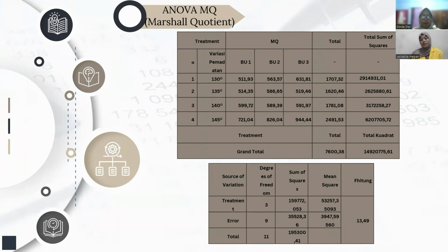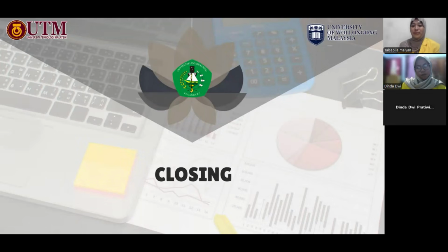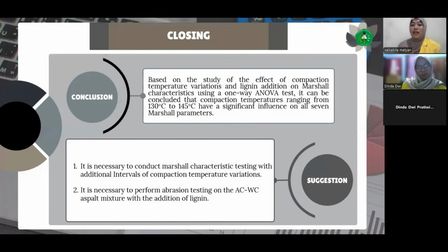Okay, then I leave it to Salsabila. Thank you, Dinda Dwi Pratiwirahayu. Next, closing. Conclusion. Based on the study of the effect of compaction temperature variance and lignin addition on Marshall characteristic using a one-way ANOVA test, it can be concluded that compaction temperature ranging from 130 degrees Celsius to 145 degrees Celsius has a significant influence on all 7 Marshall parameters.